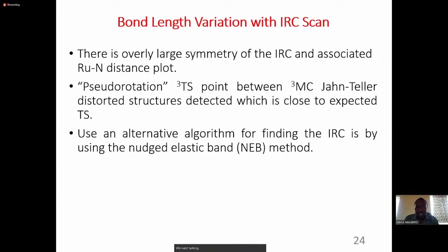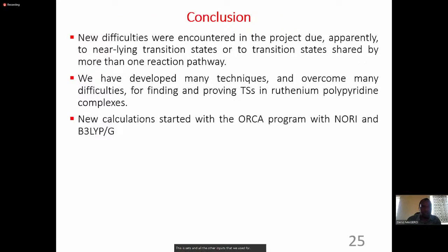We came to a conclusion that there's something called a pseudo-rotation between the triplet metal-centered Jahn-Teller distorted structures detected with those close to the expected transition state. So ideally, we have a transition state, but it is not the right transition state because of the challenges that we faced initially. We expect to solve this problem by using an alternative algorithm because you are quite close to the transition state, but you are not at the transition state that you want. By using other methods, we intend to use the nudged elastic band, which is in ORCA, using the same basis sets and all the other inputs that we used.